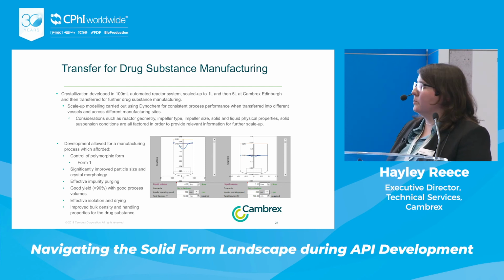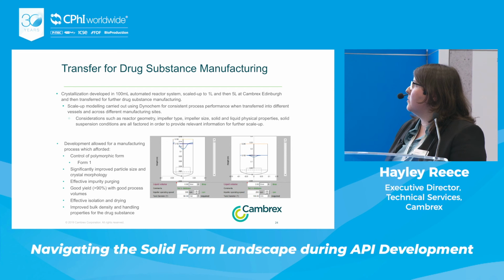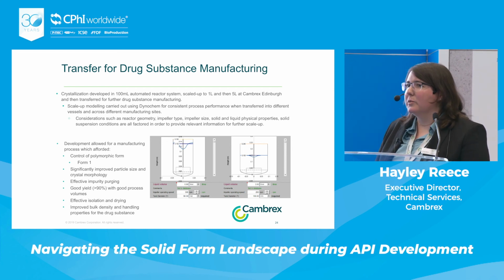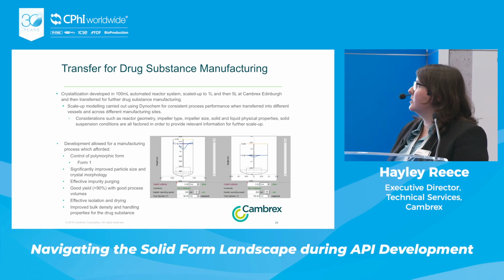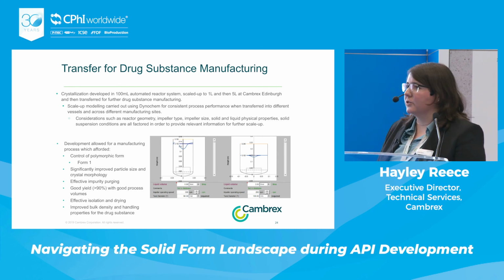What we would do is input the parameters for the reactor into Dynochem for both the smaller scale reactor as well as the larger scale, and it allows us to see what kind of mixing rates we should be using at the plant scale in order to ensure that we get consistency in the way that the crystallization proceeds. So we carried out this Dynochem modeling study, and then we were able to scale up firstly to the 5 liter reactor within our laboratories, and then transfer over to the manufacturing facility and provide this information to them on what kind of stirring rate should be used.